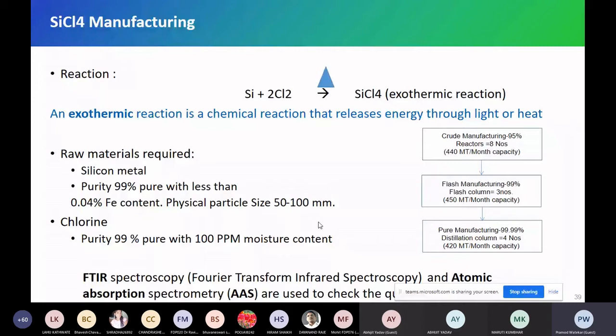In the core part, we are using imported SiCl4, because it's possible to improve this purity from 99% to 99.99%, but then there's huge investment. So we prefer to import very high purity SiCl4, 99.999 or 99.9999%. We use that for the core because light is going through the core and surrounded by cladding. We need not spend that much on expensive SiCl4 for the cladding part, which is just for protection purpose. So we have SiCl4 manufacturing there.